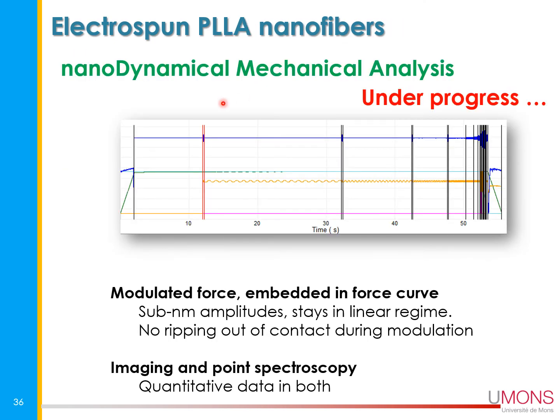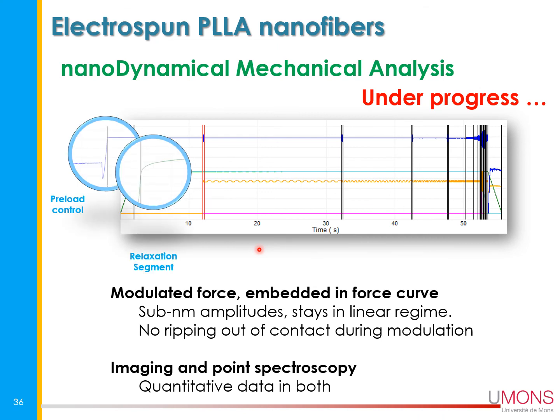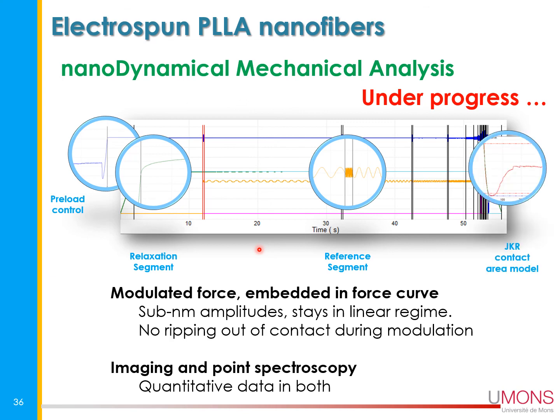So another, and I will finish with that, it's about the nano DMA. The idea is to get the mechanical properties, the viscoelastic properties, locally by using exactly what happens in the macroscopic world with DMA, dynamical mechanical analysis. And the idea is to measure the mechanical properties when you are in contact with the sample. You have the preload, and you give time to the polymer to relax, and you apply different frequencies exactly as DMA is doing, and then out of that you can get the mechanical properties. But now we are not using the DMT model, but the JKR, which is more appropriate for viscoelastic properties.